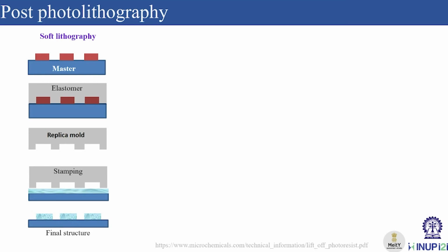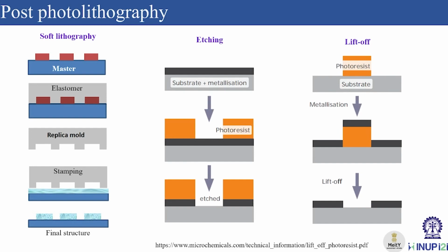Two other processes are lift off and etching, which are shown here. In the etching process, the substrate is coated with the metal, and over that the structures are developed using the photolithography technique, and after etching the structures are transferred over the metal layer. In case of lift off, first the structures are developed over the substrate using the photolithography process, over which the metal is coated, and after then lifting off this photoresist using photoresist removal, the structure is again transferred over the metal coating.